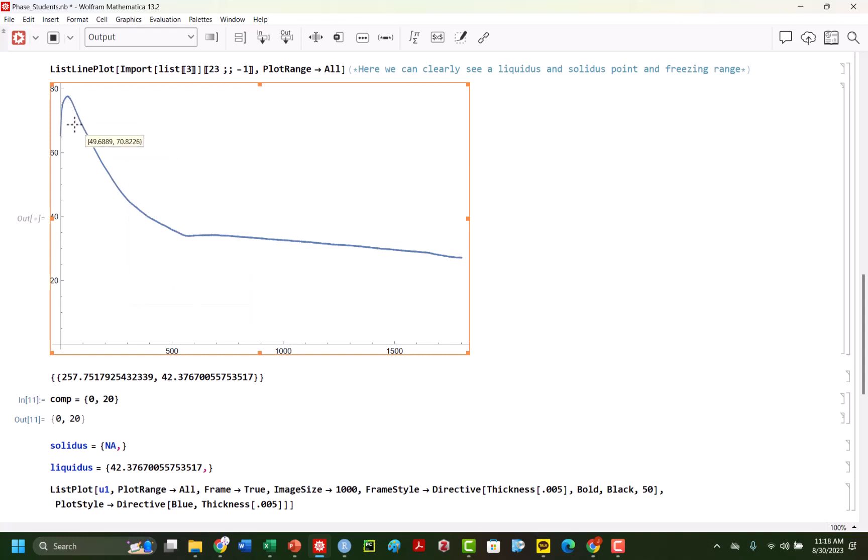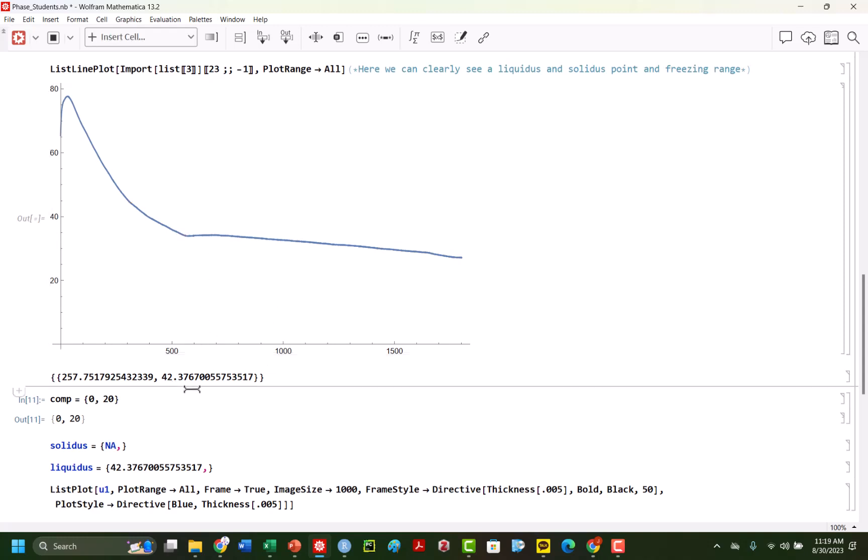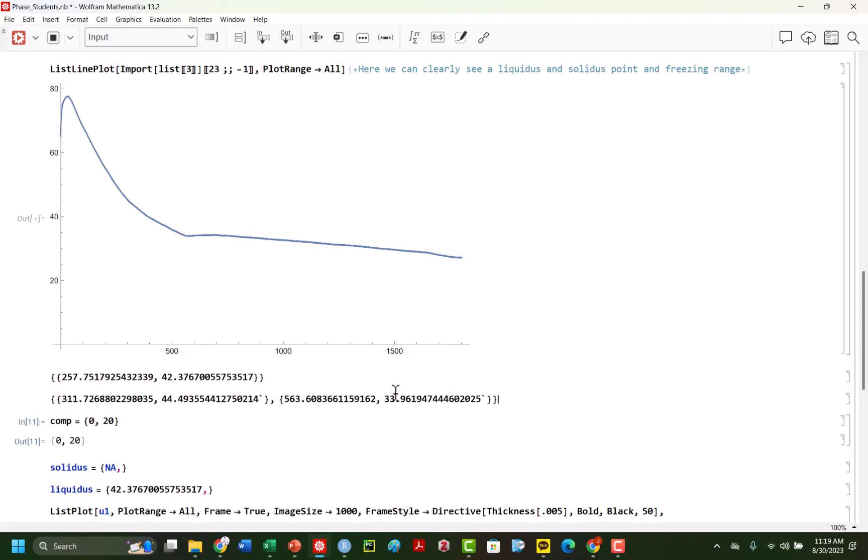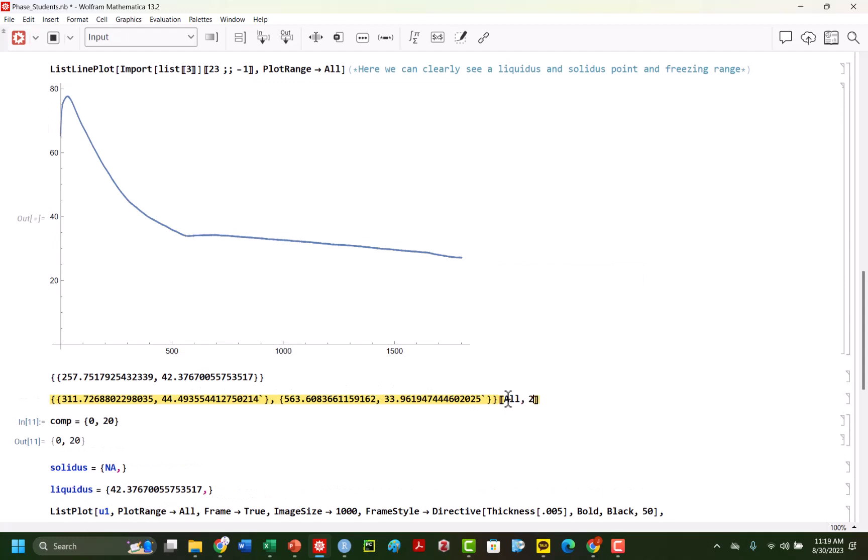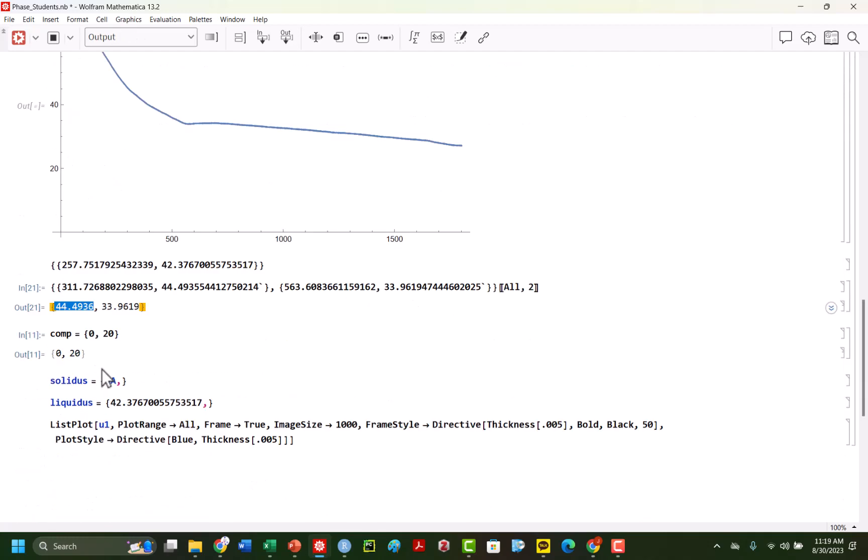So we're going to have to pick out, so we're cooling rate constant, and then you see kind of this change in slope right there. So I always like to follow along. And then you can just eyeball, you can kind of click here. So there's going to be some discrepancies based on the values you select. So I'm going to click here. And then I'm going to paste in. And I'm going to select all two. So these are my kind of two points. So the higher temperature is always the liquidus.